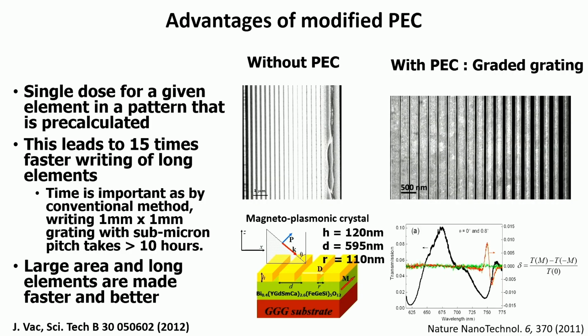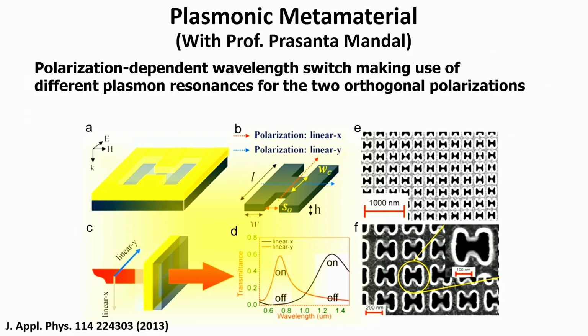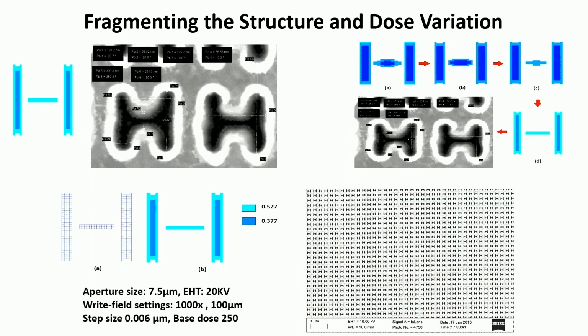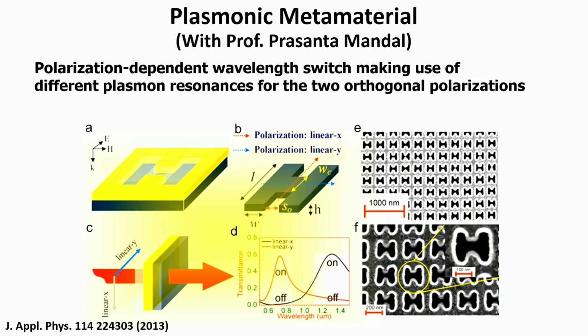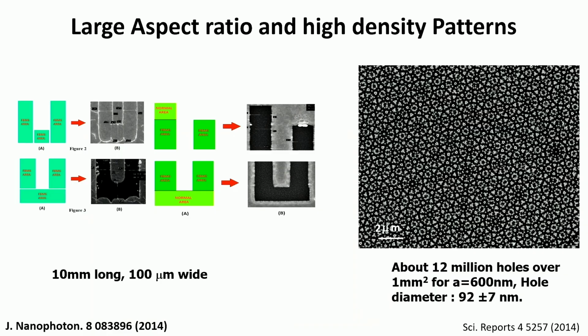So this is what went into that magnetoplasmonic structure which we have reported earlier. This is another structure. The ideal thing is we wanted to write this H-type pattern, but getting these sharp edges and non-rounded-off edges took considerable time. So we split the structure into different parts, with different doses in different parts, so that we get these structures and the response which we needed. The dimensions are so chosen that it has both 0.8 micron as well as 1.55 micron resonances. Depending on the incident polarization, we can switch the channel in this structure. Again, this is a structure with pretty long and pretty narrow lines in a U shape.